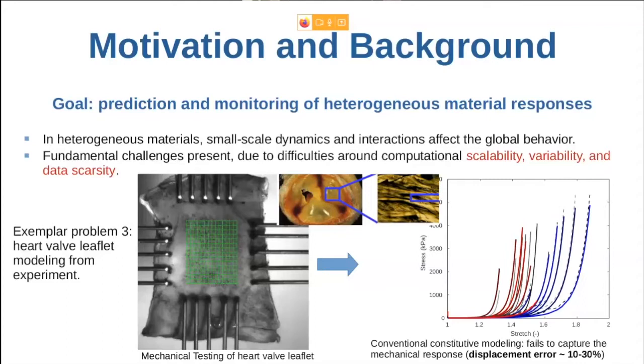So classically, how do people do that? Usually we just assume a conventional, phenomenological model, and we assume that the material is a homogenized one. Then we try to fit the parameters of this conventional constitutive model to the stretch-stress curve of the lab test. However, because you neglect the heterogeneity of the material, we usually see the displacement error is relatively large, like 10 to 30%.